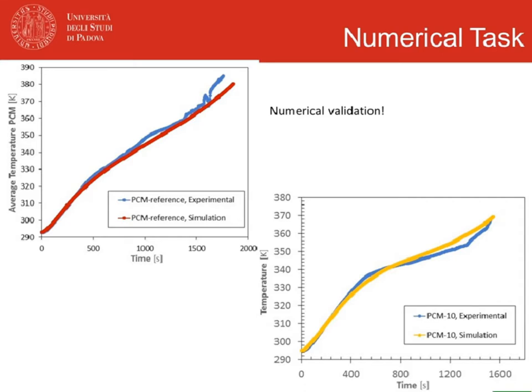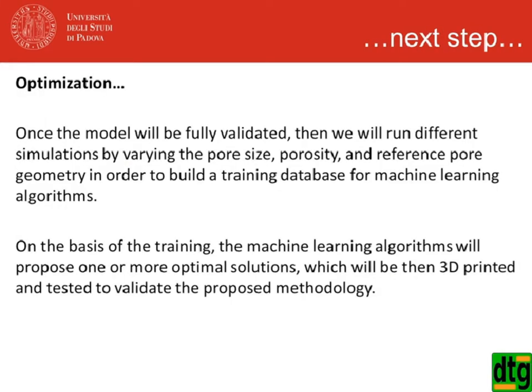PCM very accurately. And you see here the comparison between the average temperature of the PCM for the reference, so the empty box, simulated and experimental one. And of course, the same for the PCM with a 10 millimeter size structure. And you see the numerical tool is amazing in simulating the phase change process.